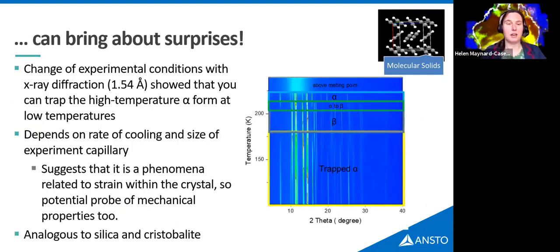But when our honours student, James, went to do it with x-rays with a smaller capillary, he found that as he cooled down, he actually got the high temperature form persisting at low temperature. And then when he warmed up, he would get the low temperature form, and then he'd get a mixture of them all. So what he discovered was that we've got the potential of phase trapping. And again, this is seen in earth minerals. So cristobalite, which is a high temperature form of silica, of quartz, cools down too quickly. A volcano erupts, it cools down too quickly, and it becomes metastably trapped at room temperature.